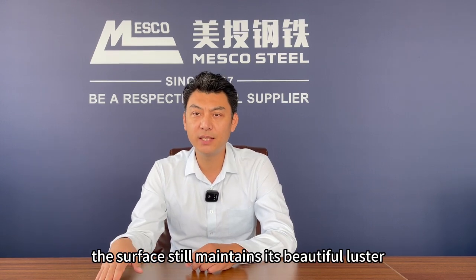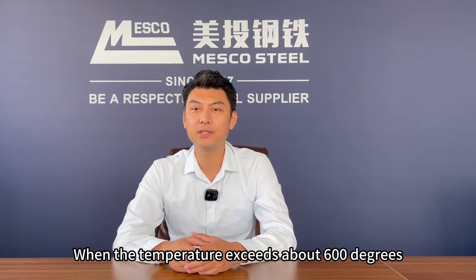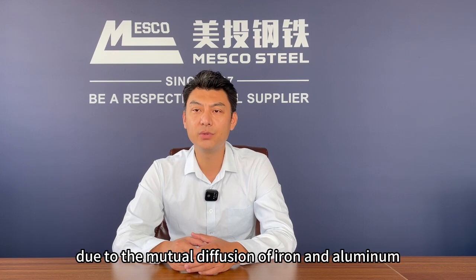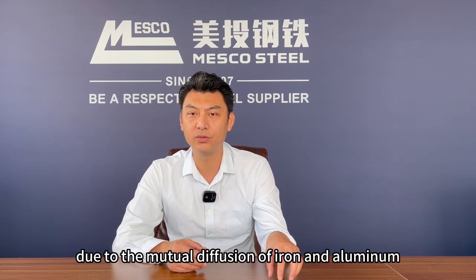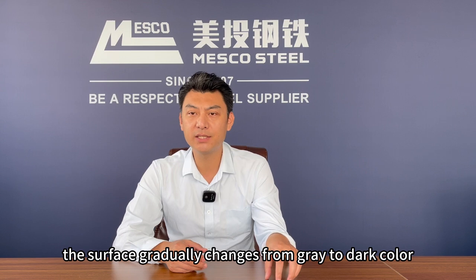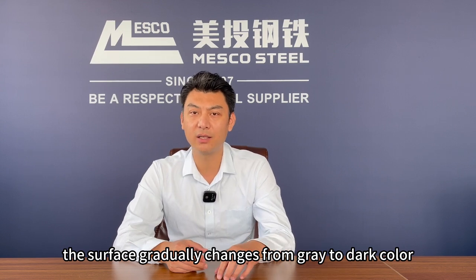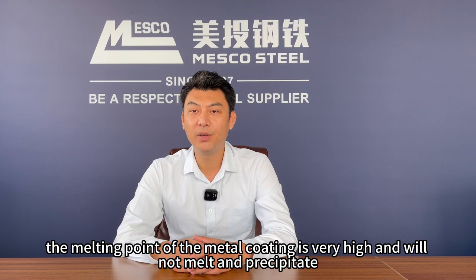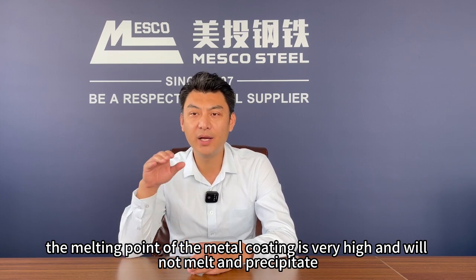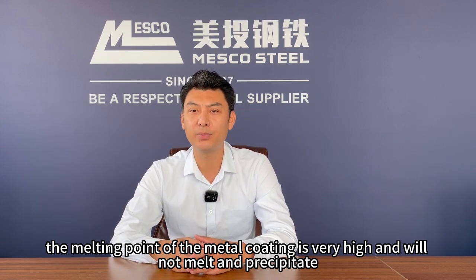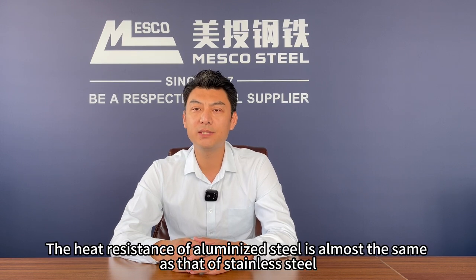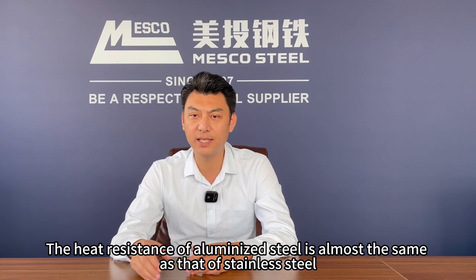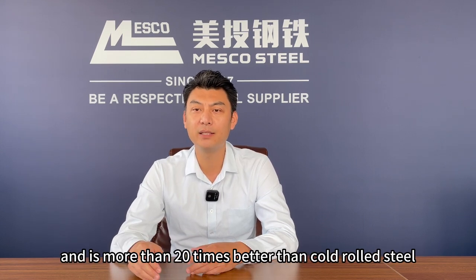The surface still maintains its beautiful luster. When the temperature exceeds about 600 degrees, due to the mutual diffusion of iron and aluminum, the surface gradually changes from gray to dark color. However, the melting point of the metal coating is very high and will not melt and precipitate. The heat resistance of aluminized steel is almost the same as that of stainless steel and is more than 20 times better than cold-rolled steel.